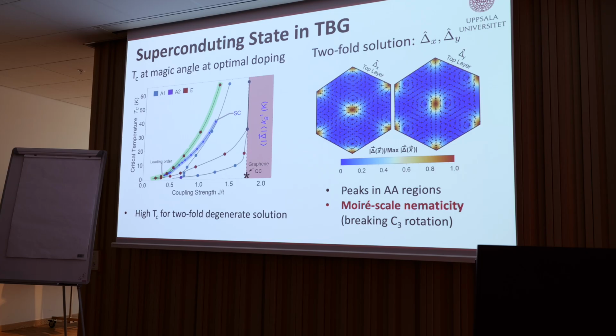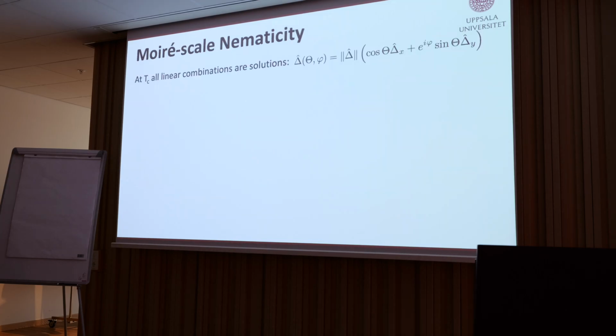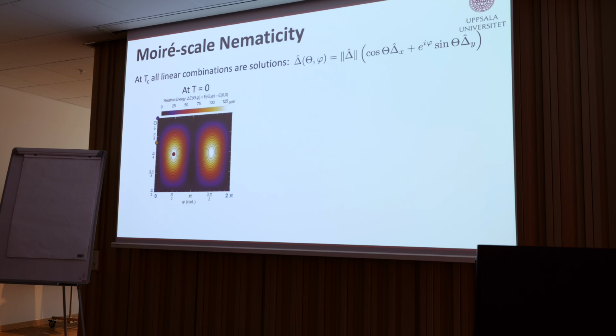And if you look a little bit more carefully at this, we can get out even more information. Technically, any combination of delta x and delta y is feasible, so you can write things up as a combination like this with some angle theta and phi, and we can see which solution wins. And this is where we find the nematic solution. So here I plot the energy difference at T equal to 0 when I change theta and phi. And the best one is the one here in the corner. That is one where theta is 0 and phi is 0, so that is a nematic solution, just delta x.